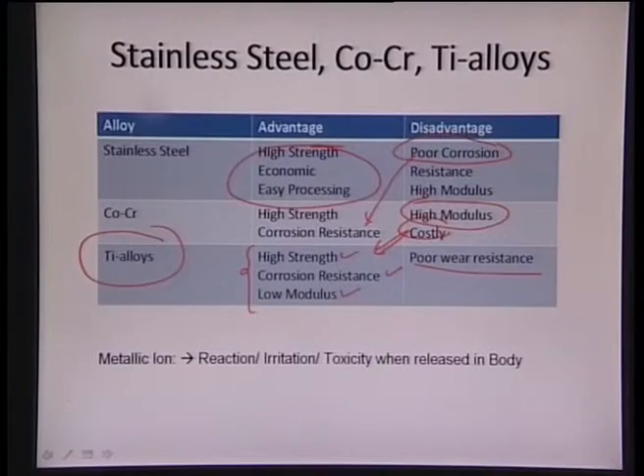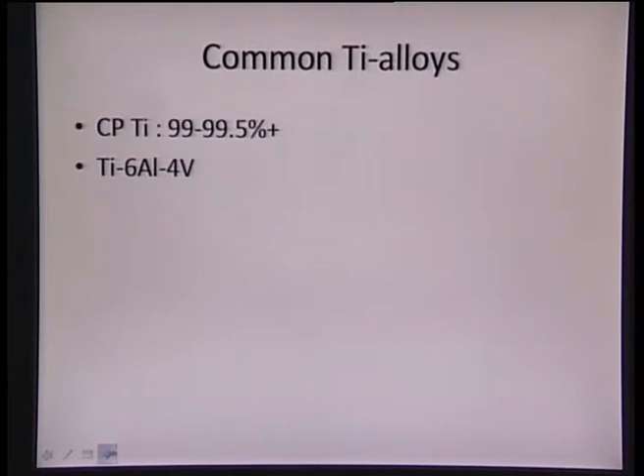There is one more problem with the titanium alloy, titanium 6 aluminum 4 vanadium: it has a metallic ion concentration, and that can react, irritate, or induce some toxicity when released into the body. In order to eliminate or reduce the effects of this ion release into the body, ceramic coatings can again come to the rescue. Ceramic coatings act as a barrier, and they don't allow the ions to flow easily from the implant surface into the body.